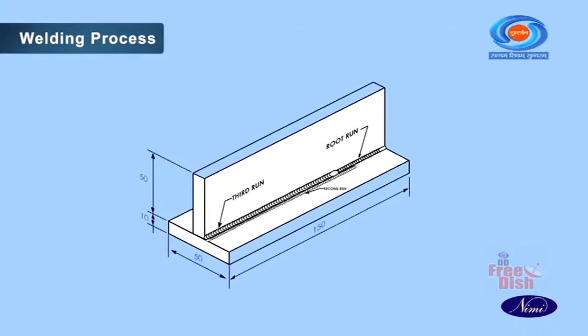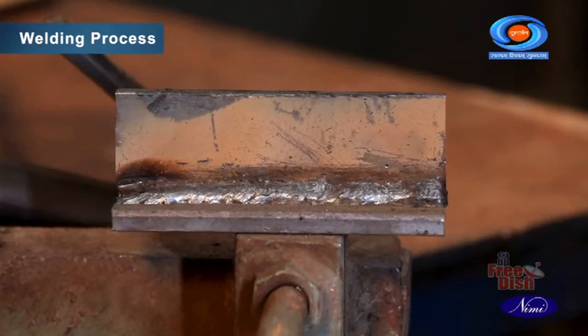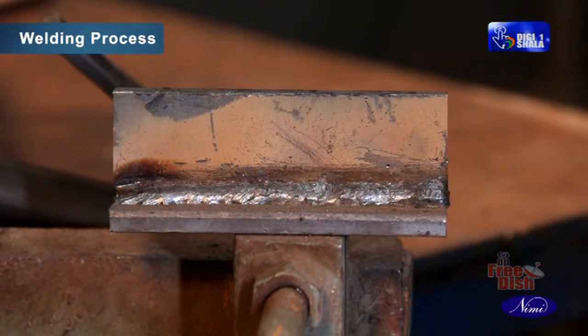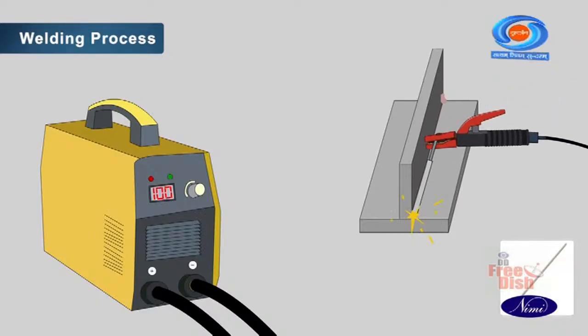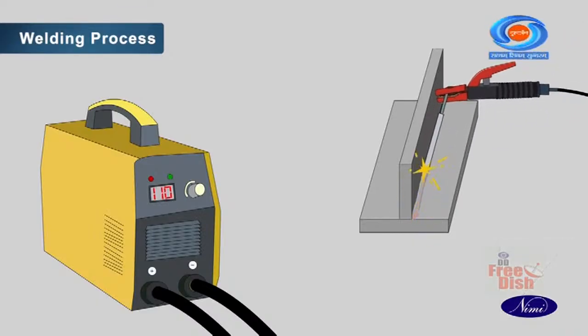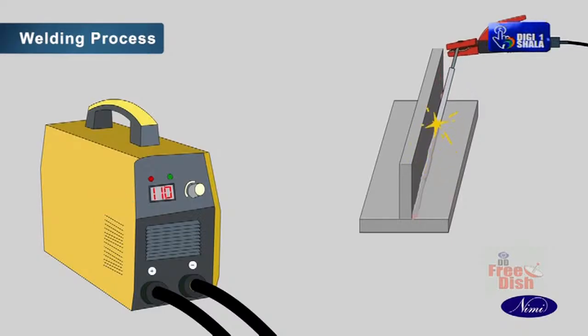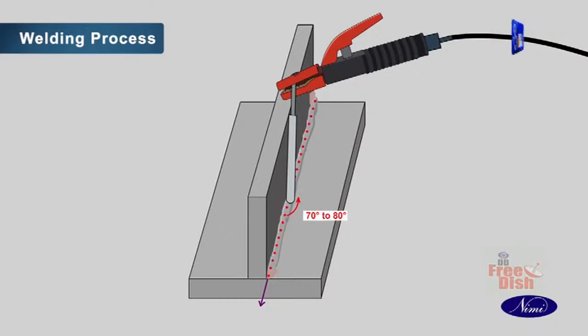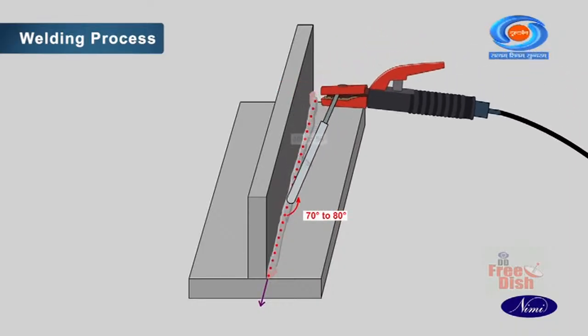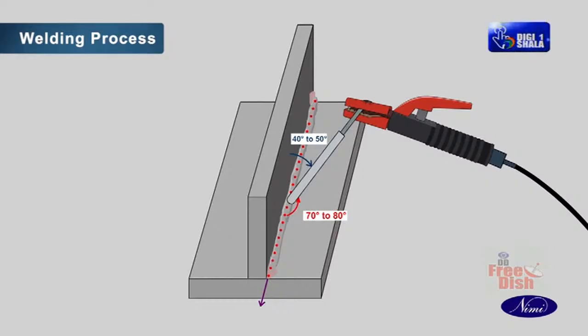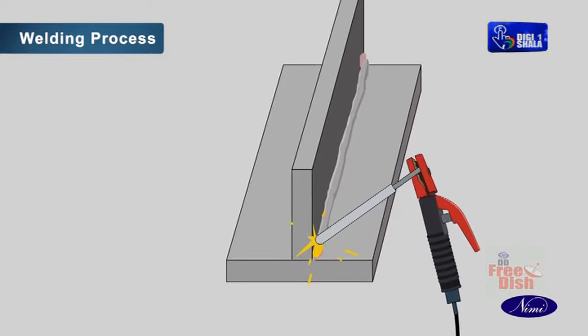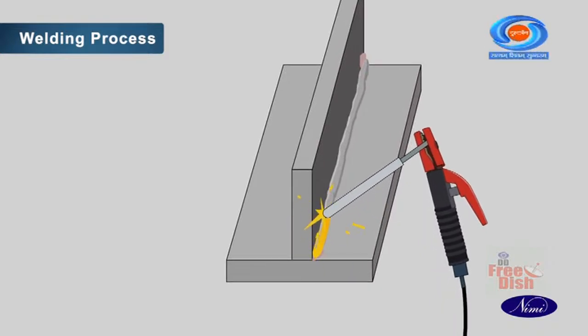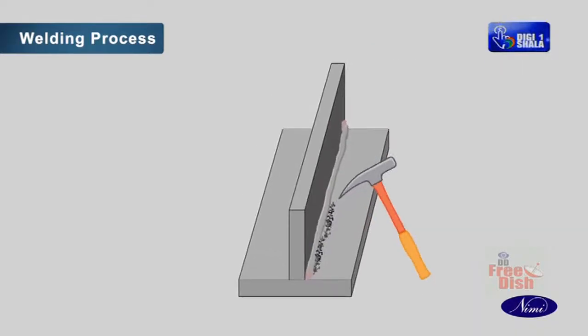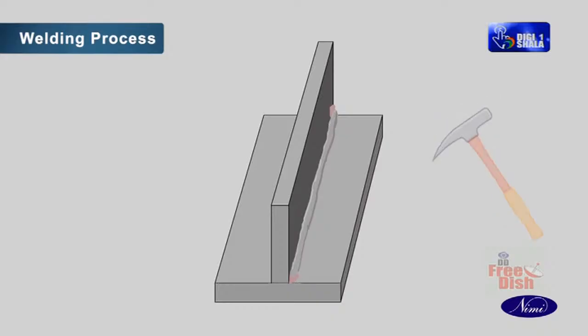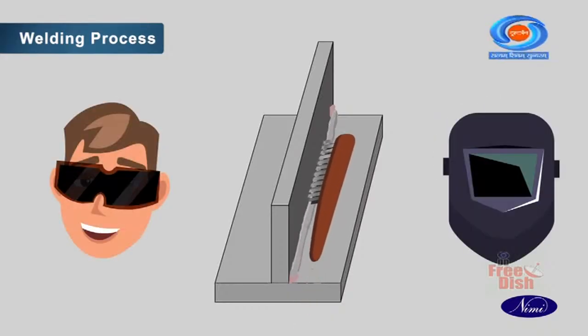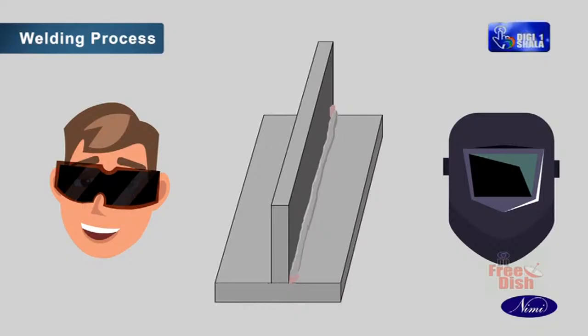Let us look at the welding process of a T-joint on 10 mm thick MS plates in horizontal position using SMAW process. Deposit root run with 3.15 mm dia electrode and 110 amps welding current, maintaining the electrode angle of 70 degrees to 80 degrees to the line of weld and 40 degrees to 50 degrees between the vertical plate and electrode. Maintain a short arc to get uniform fusion and proper root penetration. Deslag and clean the root bead thoroughly. Use safety goggles while deslagging to protect the eyes from flying slag particles.